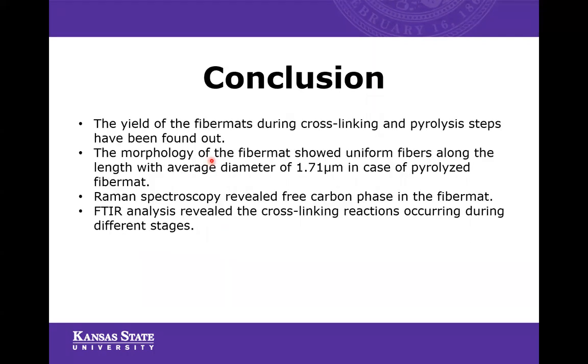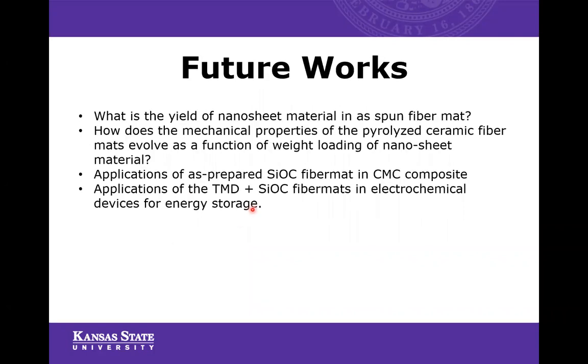To conclude, the yield of the fibermats during cross-linking and pyrolysis steps has been found out. The morphology of the fibermat, which was studied with scanning electron microscopy and transmission electron microscopy, showed uniform fibers along the length, and the average diameters were also calculated. The Raman spectroscopy revealed a free carbon phase in the fibermat, and the FTIR analysis revealed the cross-linking reaction that was occurring during different stages.